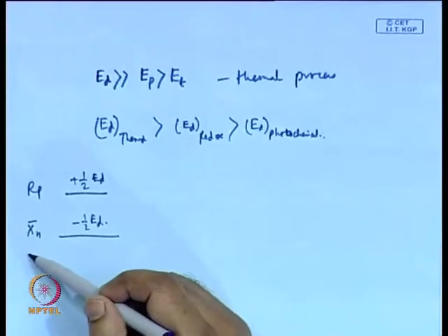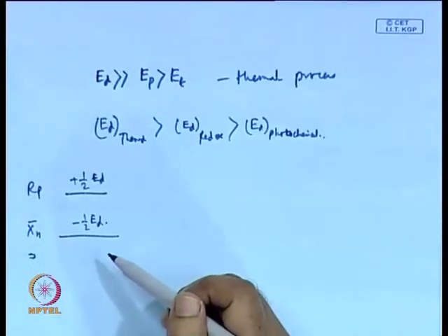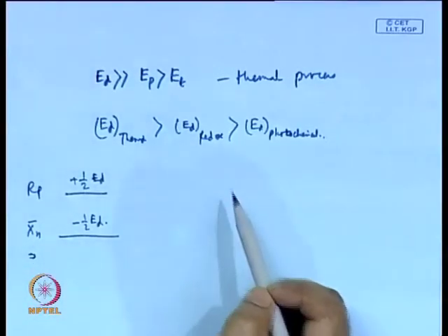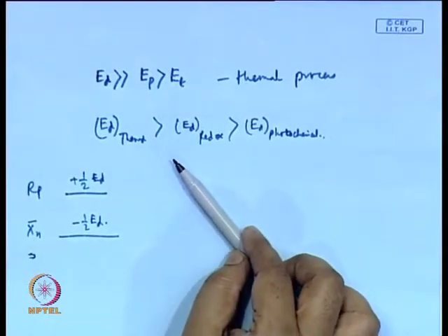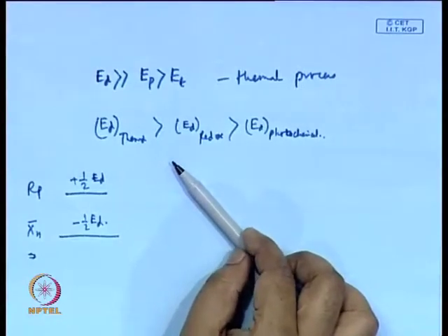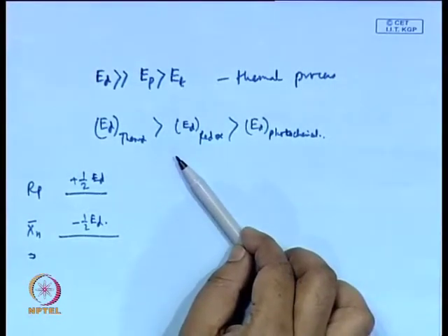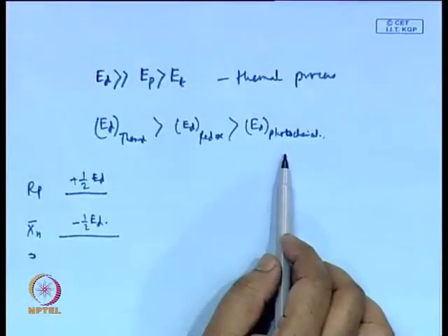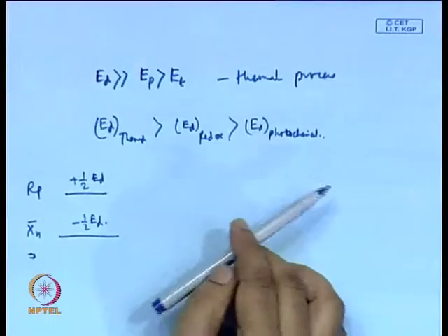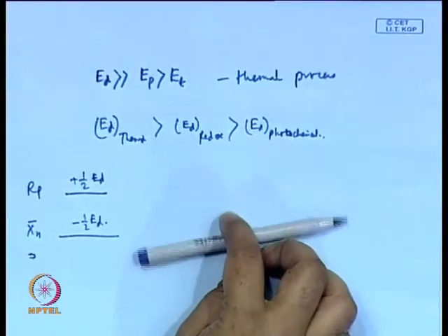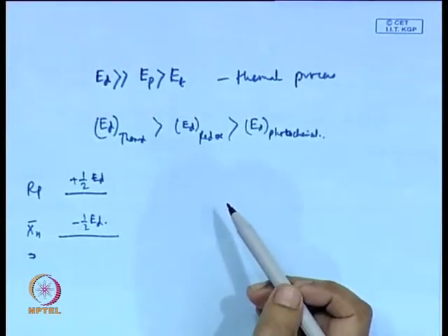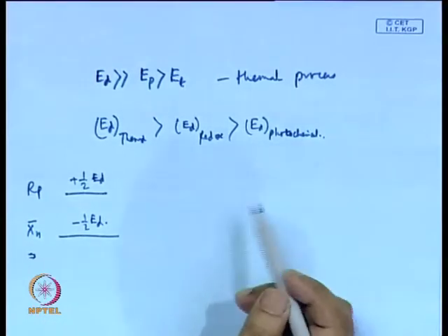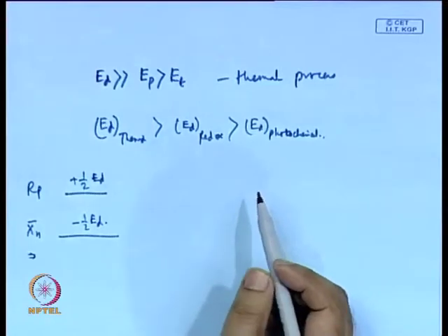In the case of molecular weight, again in a similar order, the molecular weight was dropping with increasing temperature, mostly for the thermally initiated reaction, then for the redox reaction, and for the photochemical reaction, because ED is actually 0, it was going up mildly. In the case of the photochemical reaction, we actually get a slight increase in molecular weight with increase in temperature.